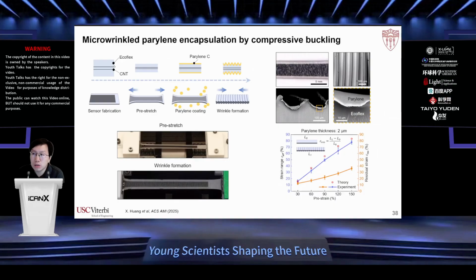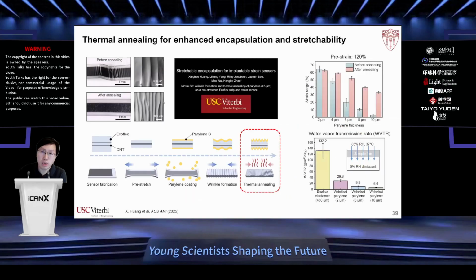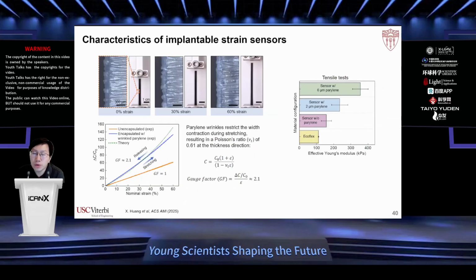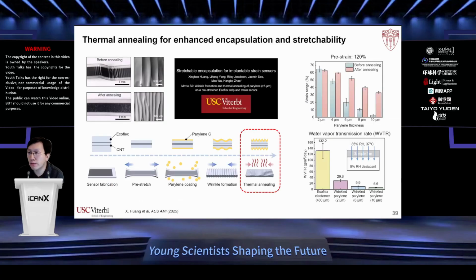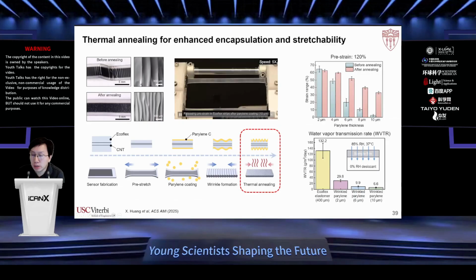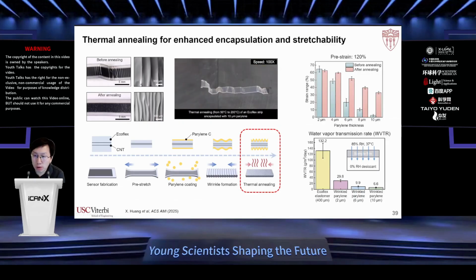I think my PowerPoint, okay, it's working. So, but another issue we found is that if we want to have good barrier performance, which means that we want to have low water penetration, we have to use very thick parylene. So one issue of that is that when we release the sensor, instead of forming micro wrinkles, we will have global buckling.